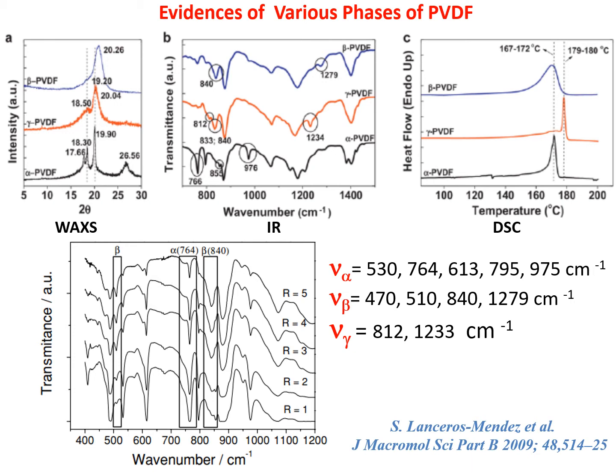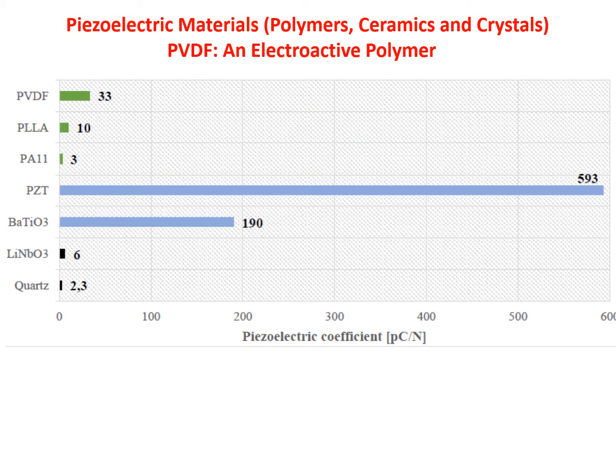So these techniques are very straightforward in order to characterize and to enhance and evidence the presence. Another very important parameter is the piezoelectric parameter. PVDF has a piezoelectric coefficient of 33, which is the highest for polymers. Polylactide is also about 10. It's rather surprising. Polyamide 11 is 3. PZT, so lead, zirconium, titanium, almost 600, which is the king of the piezoelectric parameter.